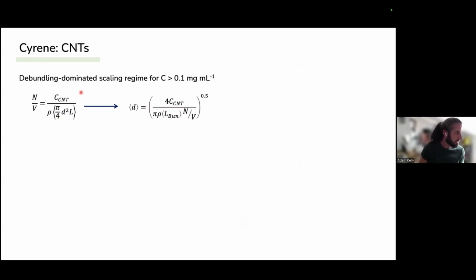So to quantify this and to fit the data, we take the number volume, which is the number of nanotubes or number of bundles per volume, which is equal to the concentration, the milligrams per milliliter, over the average bundle mass. So reformulating this equation gives us this value here, which is the diameter, now in terms of the concentration, the density of the nanotubes, and the length of the bundles.